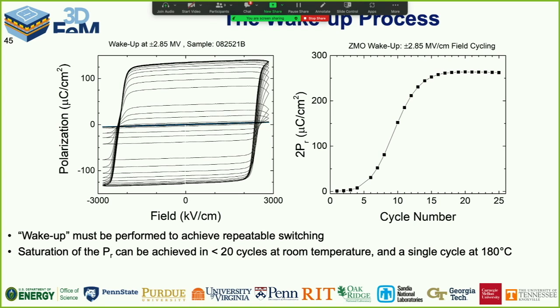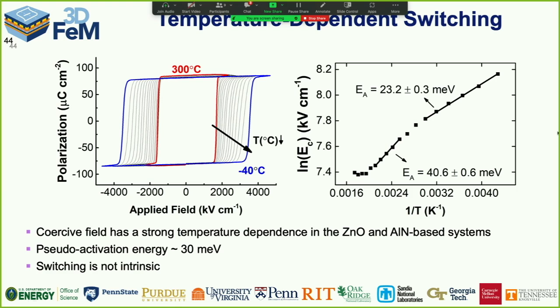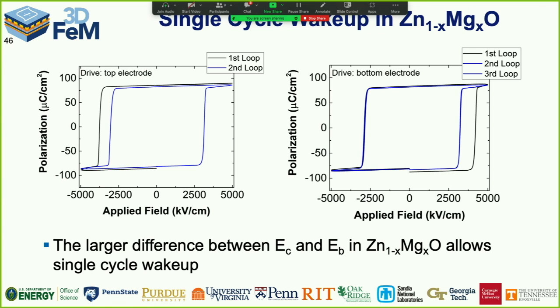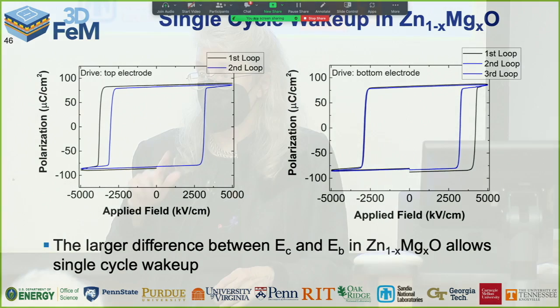The wake up here is actually a little easier to study because these materials have a bigger difference between the coercive field and the maximum field the material will tolerate. So I can just jack the field up and study it at higher electric fields. And so we've demonstrated that you can actually do single cycle wake up in this. So one application of a large voltage and you run through the entire ferroelectric hysteresis loop. So that looks like a second really promising candidate.